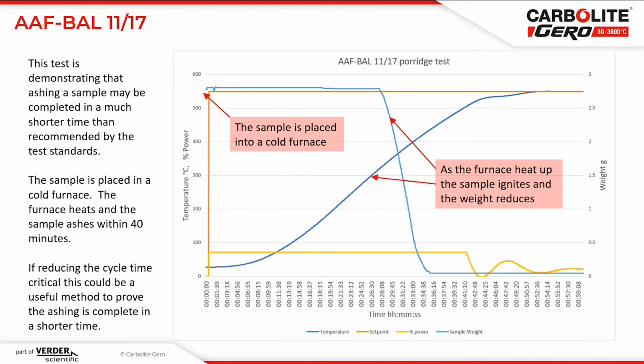So if we look in more detail at the graph that we were showing there, we're investigating if we could reduce the cycle time of an ashing application. As Tom described earlier, we were looking at seeing if we could do that by monitoring the temperatures in the chamber. And here we can do this by monitoring the weight of the sample. So in the graph, what's happening is we're putting a sample into a cold furnace, and then we're setting the set point to 550 degrees C. And we can see that the ashing of the sample was complete, in fact, before the furnace even reached 550 degrees C. So the furnace heats and the sample ashes within 40 minutes.